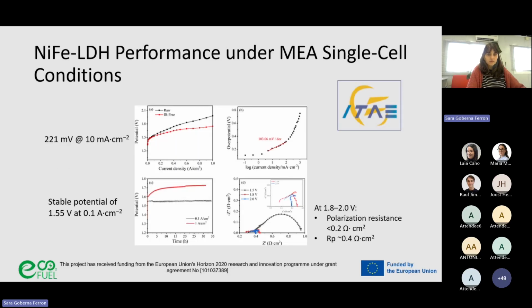So first of all, here we can see the polarization curve. We observe that our nickel iron LDH catalyst reaches 10 milliamps per square centimeter at an overpotential of 220 millivolts, which already indicates a very good activity for the oxygen evolution reaction. The corresponding Tafel slope, which is close to 100 millivolts per decade, suggests reasonably fast reaction kinetics.